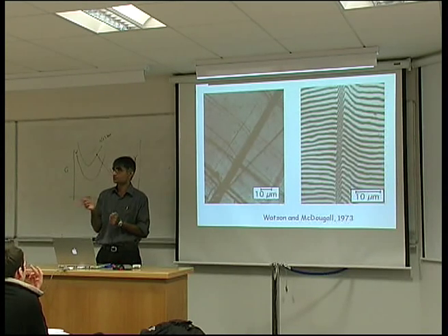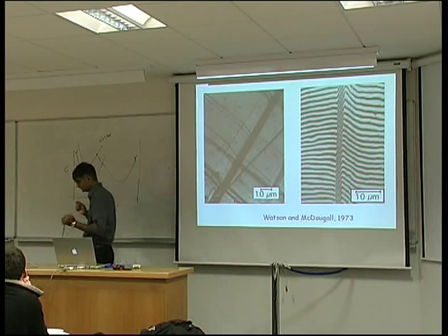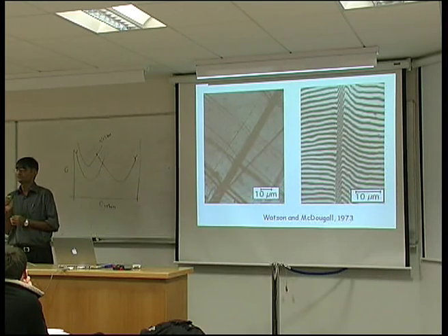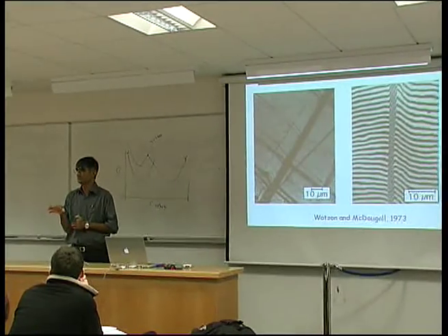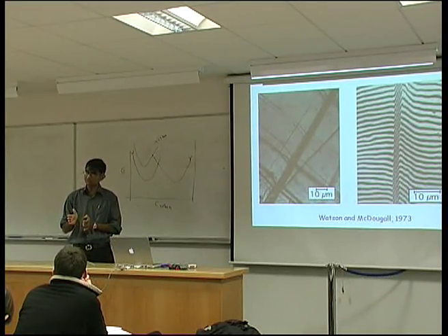Carbon must partition during its growth, and the displacive transformation must occur at a rate which allows that carbon to partition. And that's the reason why I said to you that martensite doesn't have to grow at the speed of sound in the metal. It can grow at that speed, but it doesn't have to. You can get a displacive transformation which is slow.